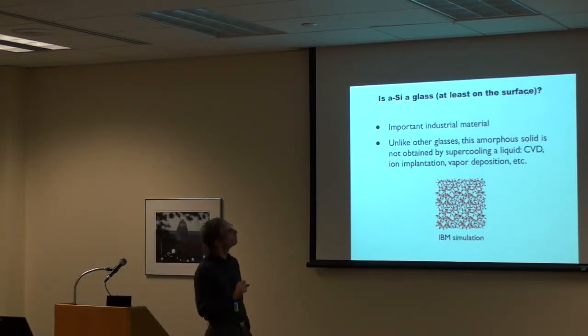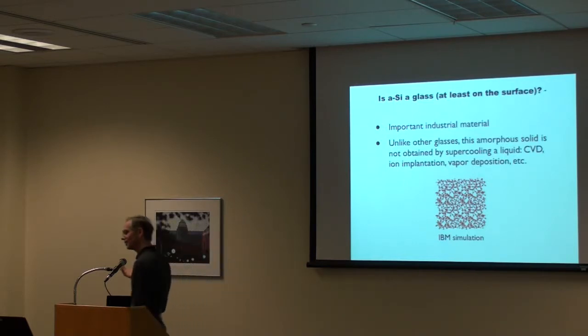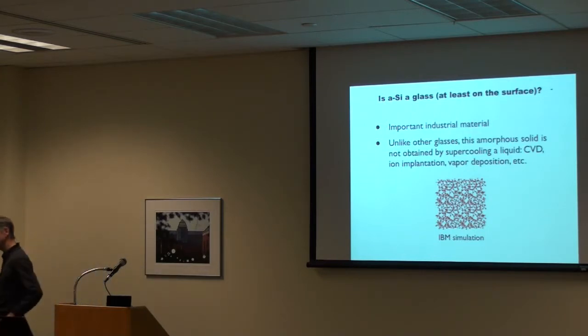It has a very weird property, which is that unlike other glasses, this particular amorphous solid, and we all agree that amorphous silicon is an amorphous solid, is not obtained by supercooling a liquid. So normally the way you make a glass is you take a liquid and you just cool it quickly enough so that the molecules or atoms in the liquid cannot move into their crystalline positions. Okay? And you're kind of just freezing the liquid in a conformational state that still looks somewhat liquid-like, so it's random. But the viscosity is so high because you're at low temperature, it doesn't move anymore. So it's kind of like a liquid that's stuck. Okay? And that's how glasses are normally made. And then you could observe the glass transition and so forth.